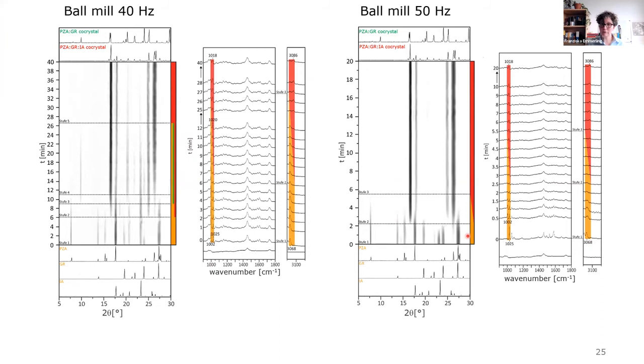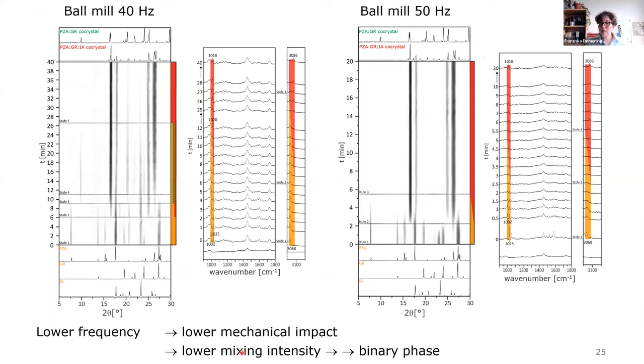And we rationalized that we see the binary compound in this case before, because we have lower mechanical impact and also lower mixing intensity, and therefore it's harder for three components to form the ternary co-crystal, and the binary phase is preferred in this case.